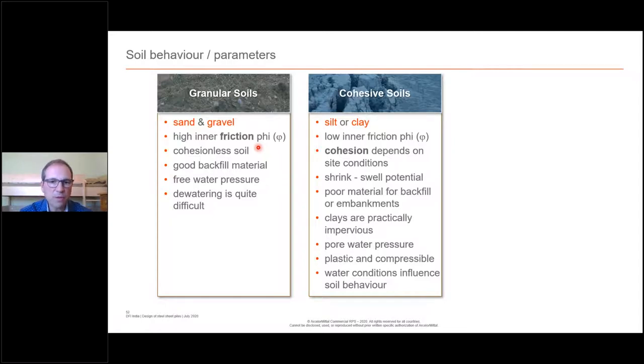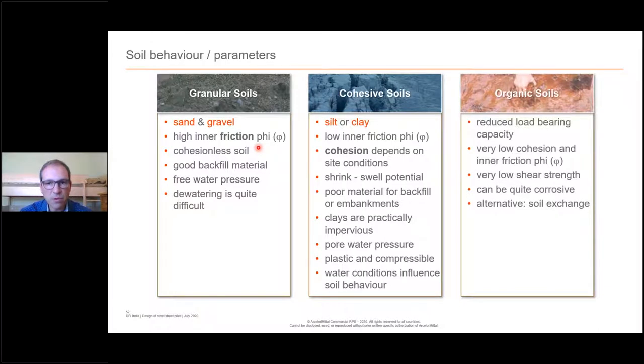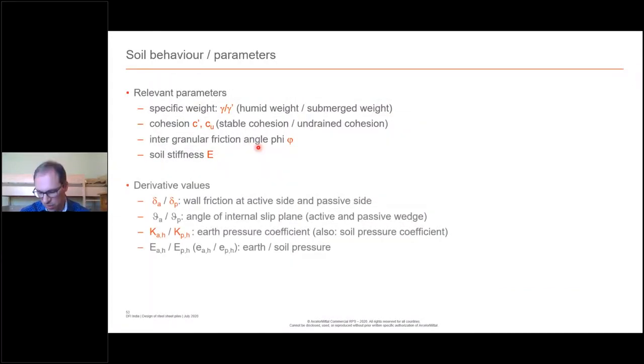And then you have to be careful also about analyzing both situations, so undrained and drained. It shrinks sometimes, and as I said, it's poor material for backfill. And then you have what we call organic soils, which, well, you have to cope with. For instance, in the Netherlands, they have peat over a couple of meters at the shallow depths. So they have to deal with it because they cannot simply replace it. But sometimes when you have the choice to replace it or to improve it, that's what you would be doing rather than coping with the bad soil parameters.